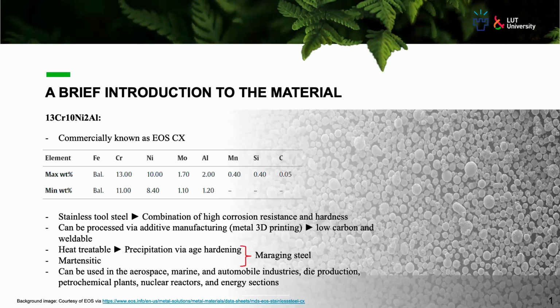So in its nature, it's a stainless steel, considering the high amount of chromium, and considering its hardness values in the range of 300 to 450 Vickers, it's considered a tool steel. The combination of high corrosion resistance and hardness makes it a very versatile material. Another great point about this material is that it can be processed via additive manufacturing.